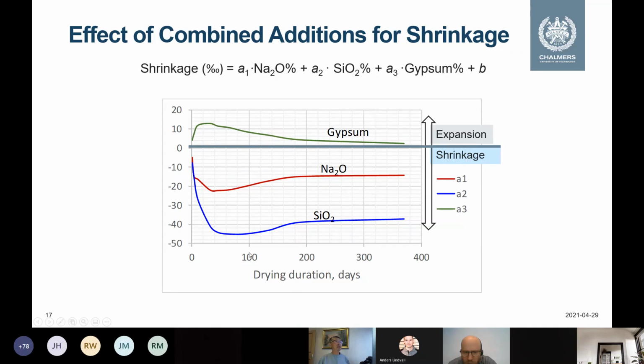After hundreds of days, you can see gypsum has already reduced its expansion. Then sodium and alkali also become more stable. So after about 200 days, we can see that sodium and silicate contribute to the shrinkage in different ways.